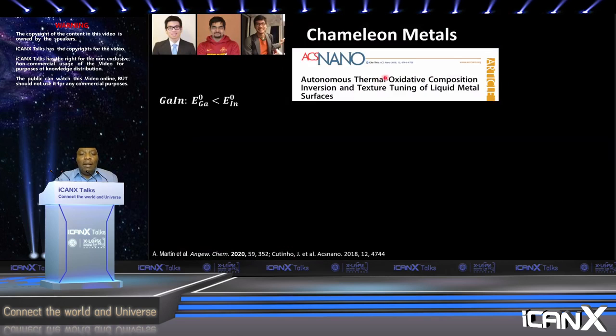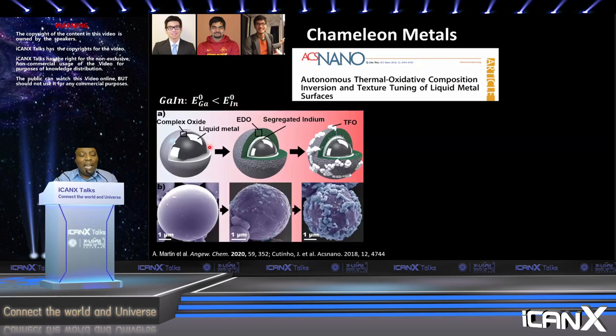Right. Now, moving on to the next section, and this work was actually first published in ACS Nano. And it came from our discussion about the distribution of the component of the surface. And we argued that if the components that are distributed on the surface of this gallium indium are actually gallium on the surface, but indium near the metal oxide interface, then we should be able to grow this oxide enough to a point that we accumulate the indium at the interface. And then when the now thickened oxide fractures by thermal stress, it would release very slowly a component that is actually rich in indium.